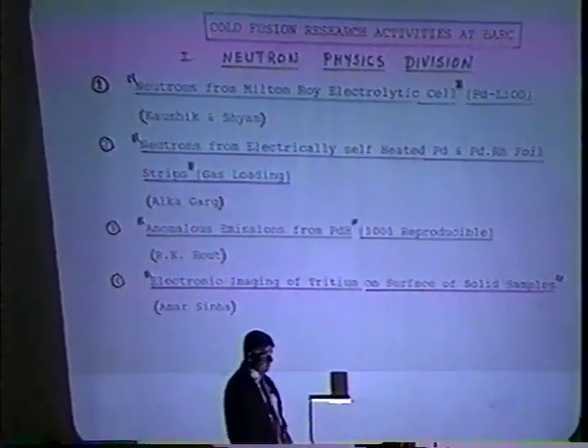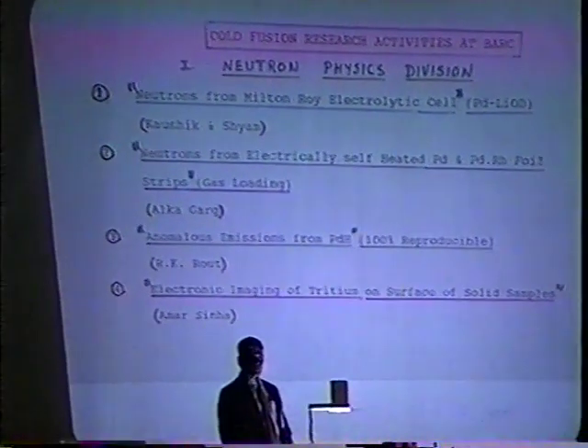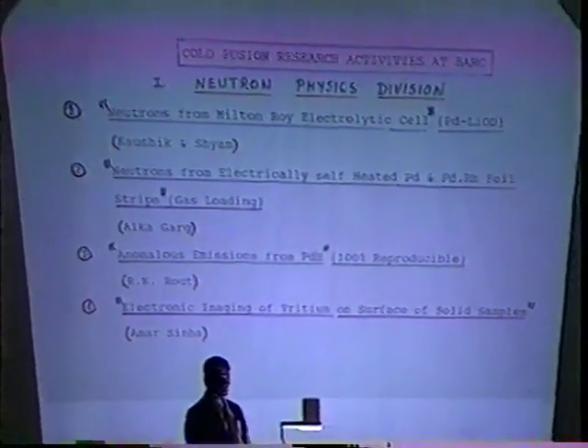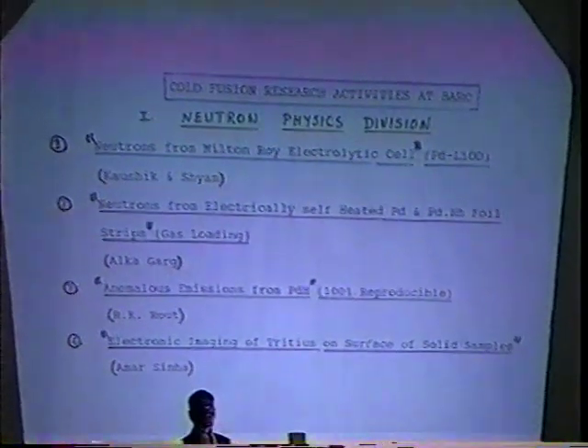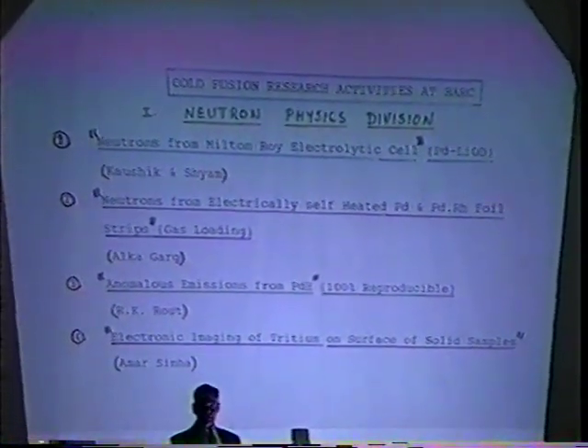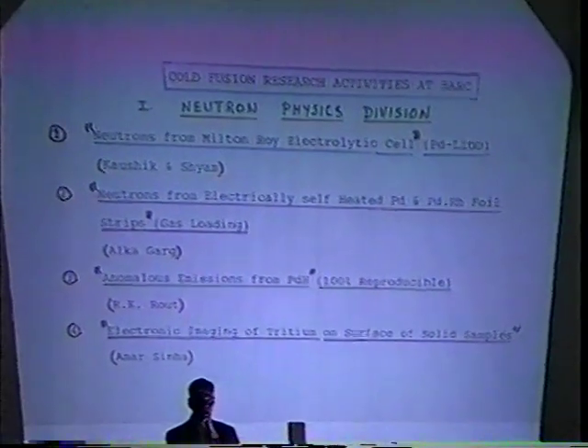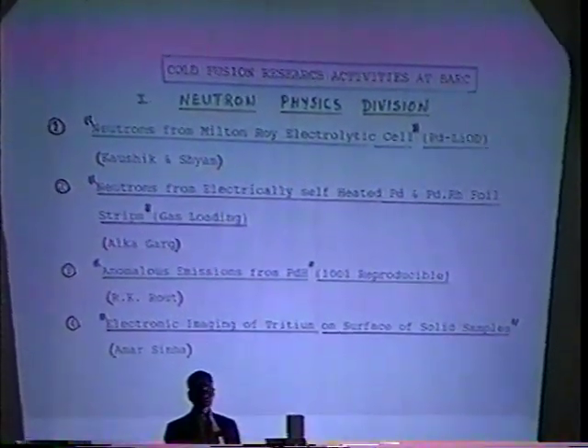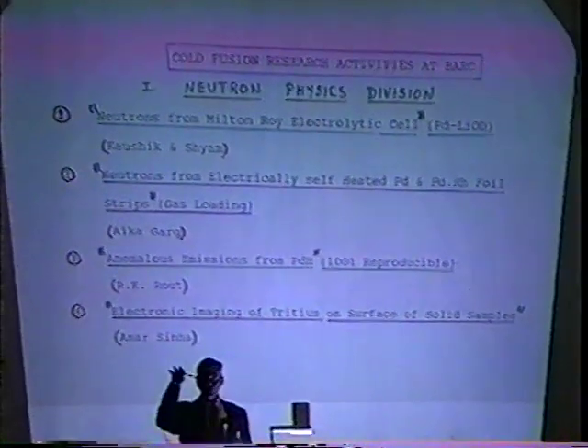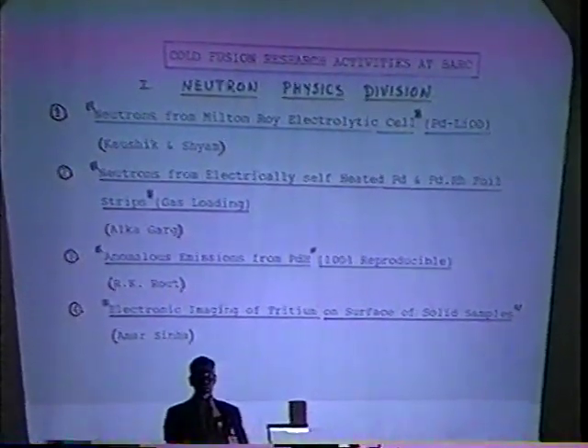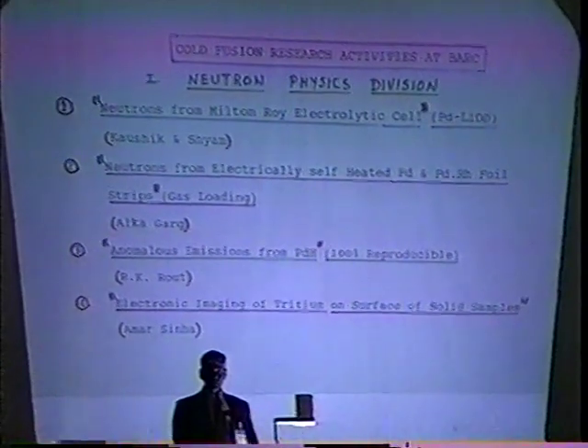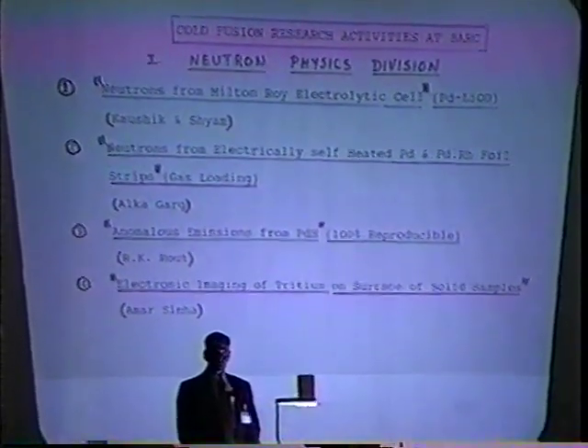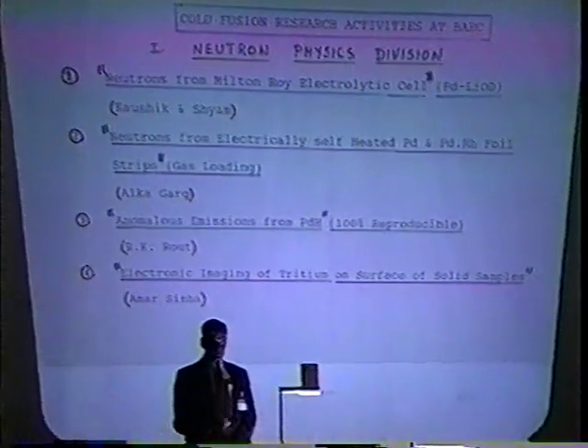But one little point we missed there was we did not take counts with the cell switched off. So many people, even at the ICCF-6, asked me the question: how do you know that the increase in count rate is not simply because you are introducing a cell containing heavy water and palladium into the counter? So that was the point which we had missed, although we ran the cell with light water, which we reported there.